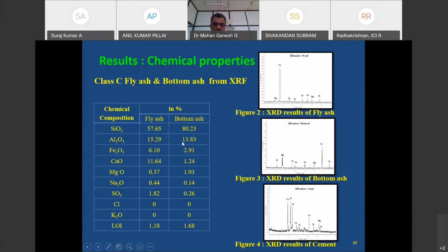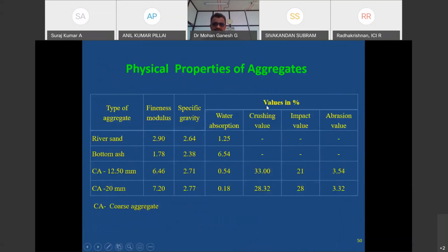So the properties of fly ash and bottom ash are comparable with cement and sand. So we have done for further work the physical properties of the aggregate. This is the value for our material, what we have used: river sand, bottom ash, fineness modulus, specific gravity, and water absorption. And coarse aggregate 12.5 and 20 mm. These are all the various values which we have compared with our manufactured fly ash aggregates.